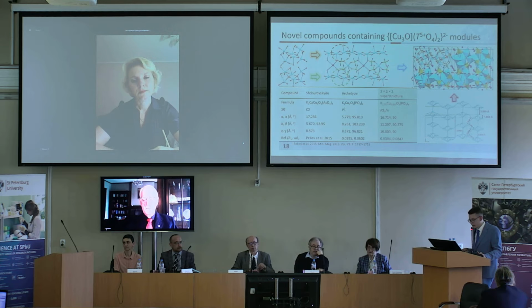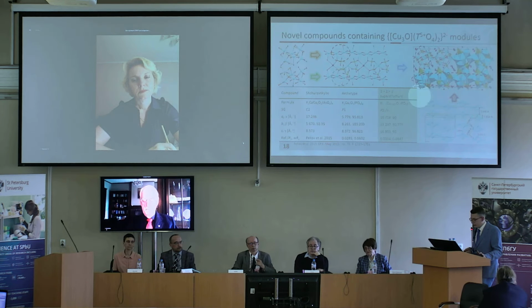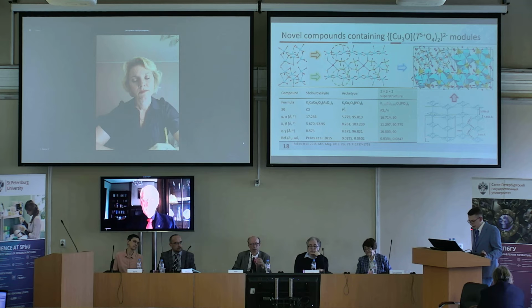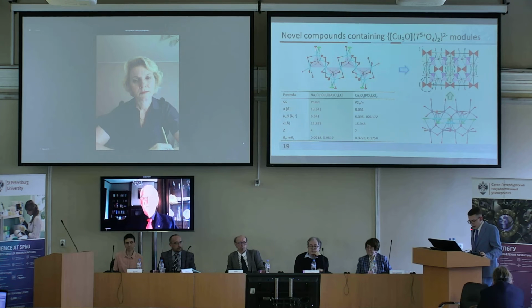The second new compound is a superstructure with an 8-fold larger cell, which also demonstrates a different chain arrangement. Conventionally, this topology can be called intermediate between the structure Shurovskite and archetype. We can see the chains are still shifted, but the symmetry of the topology is higher than in the archetype structure. The framework of this compound is characteristic not only for compounds with dimers of oxo-centered tetrahedrons.